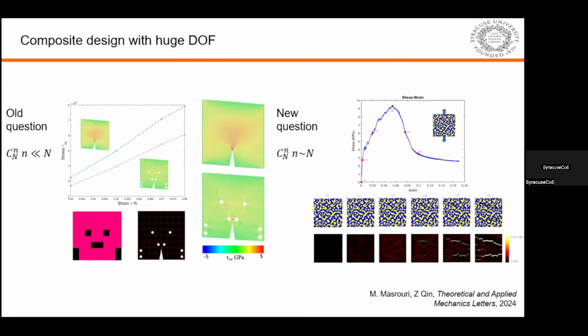But another thing, like for bamboo, the silica particle, so that's similar to deciding the location of the soft material. So that's an old question because consider the possibilities. Changing the position of the particle or changing a few soft pixels, that has a few degrees of freedom. But if you consider the entire region, and the rigid material and soft material are almost a similar amount, then the probability will be much more. And that might not be able to be effectively solved by the previous method.